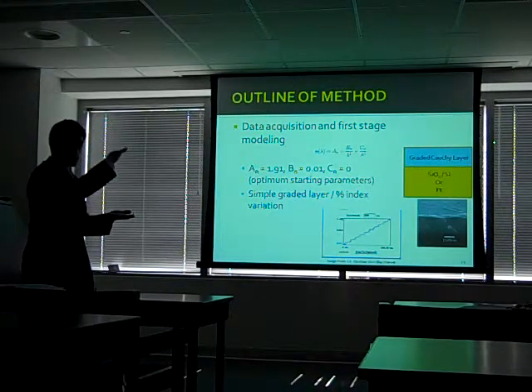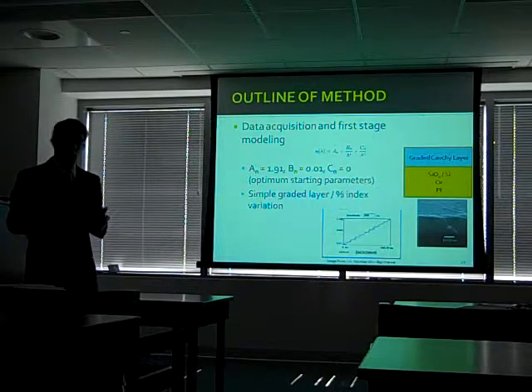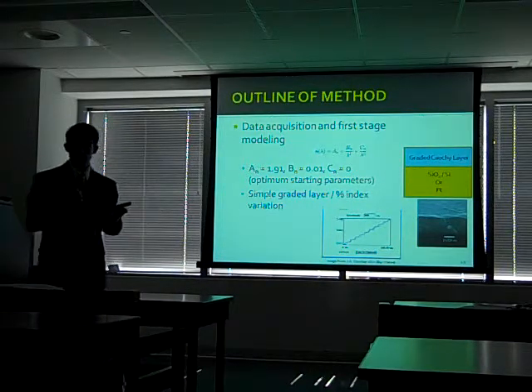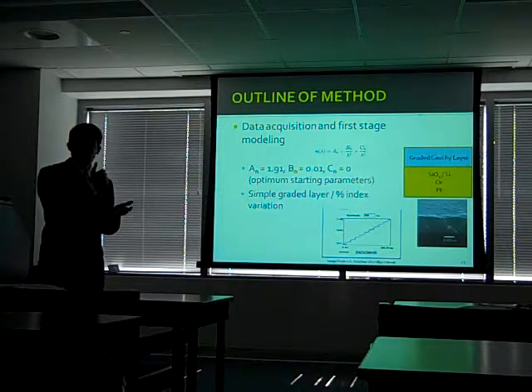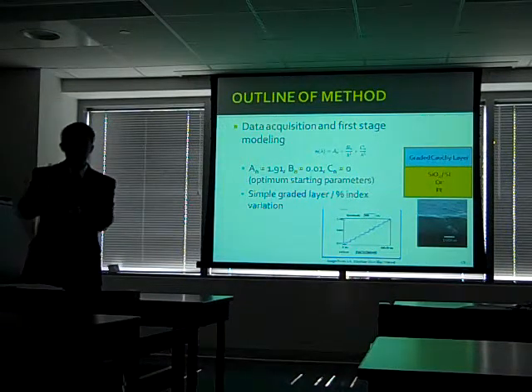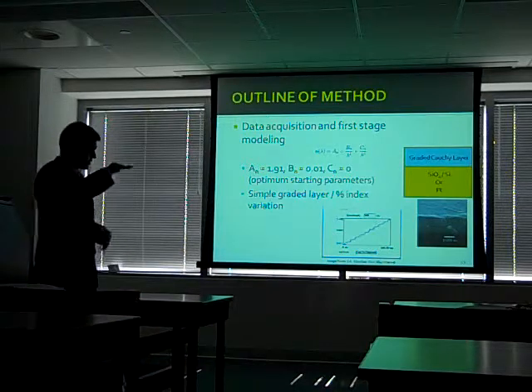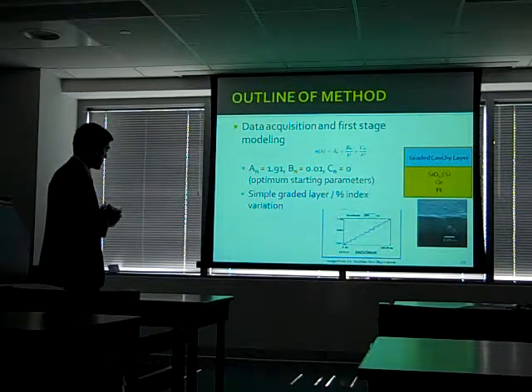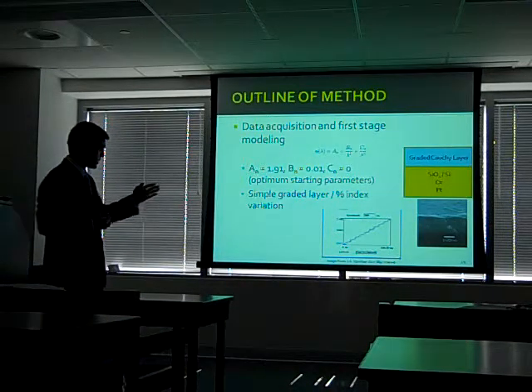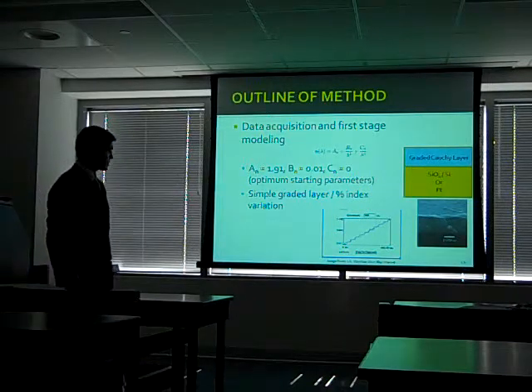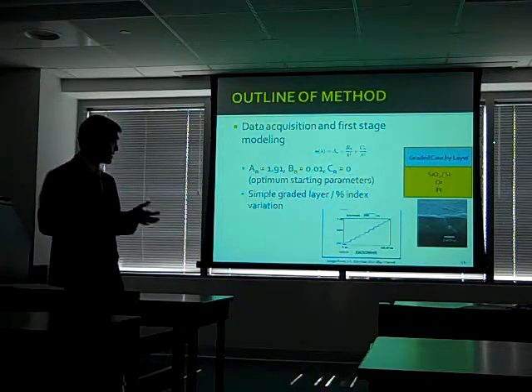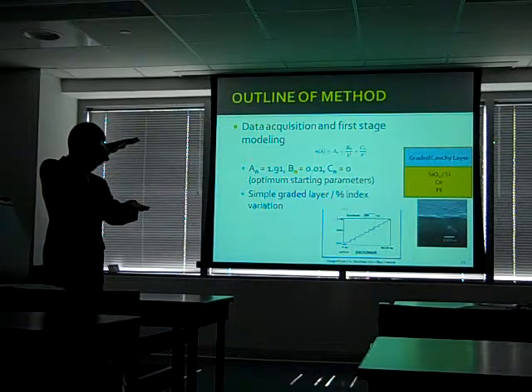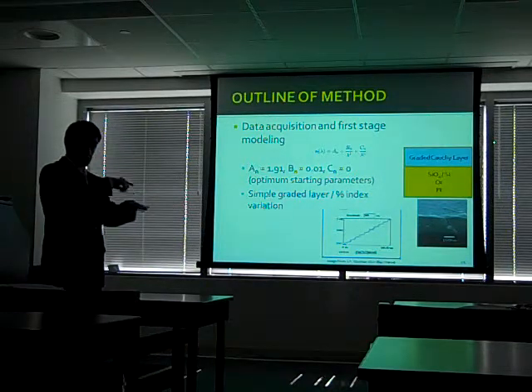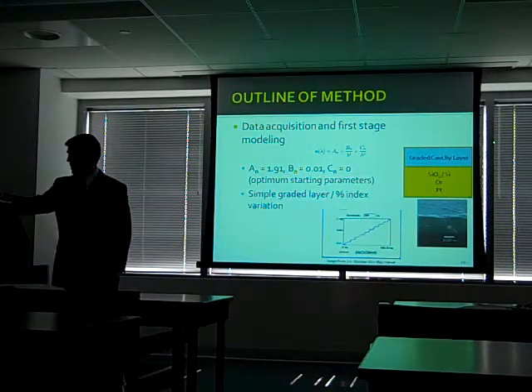So you can define the number of steps. I found that 7 works the best, and makes sense when you consider that these films are produced by the MOD technique, and so they would have 5 to 7 spin coat pyrolyzed steps. So it's a possible explanation. But again, the result is an improved fit. This also introduced a new fitting parameter, which is percent index variation, and that describes the variation of the index across this thickness.